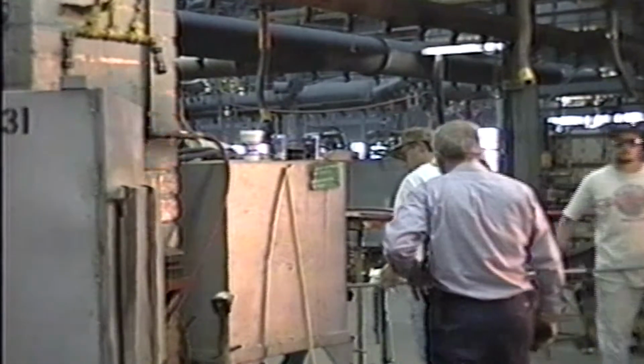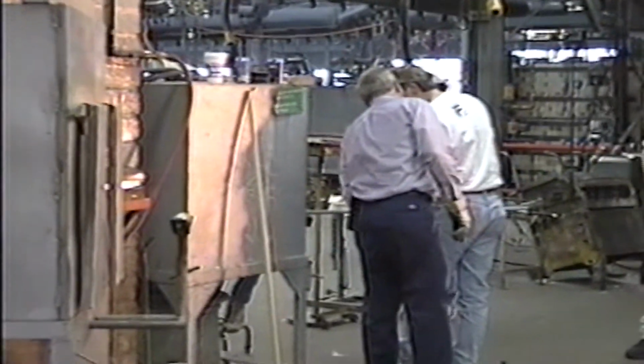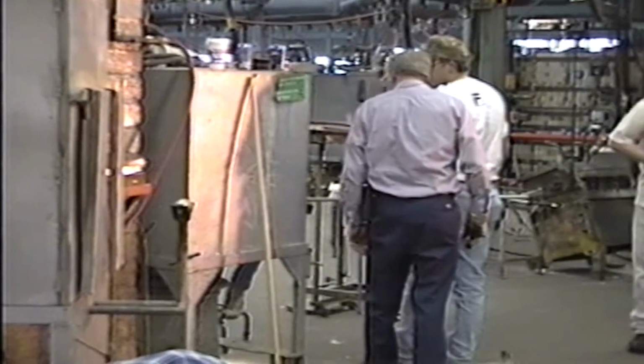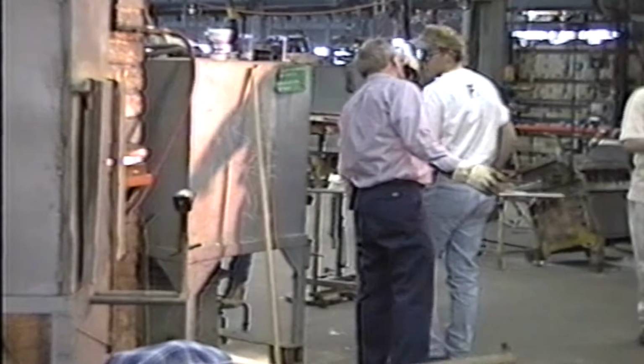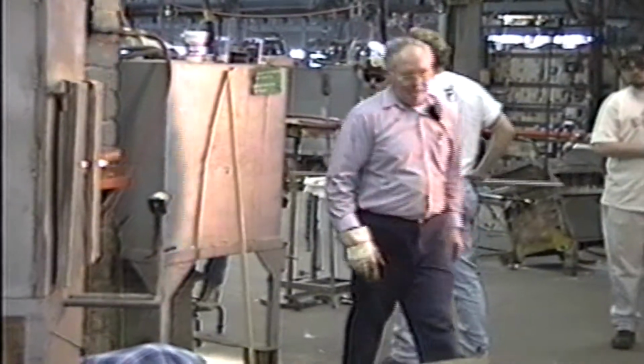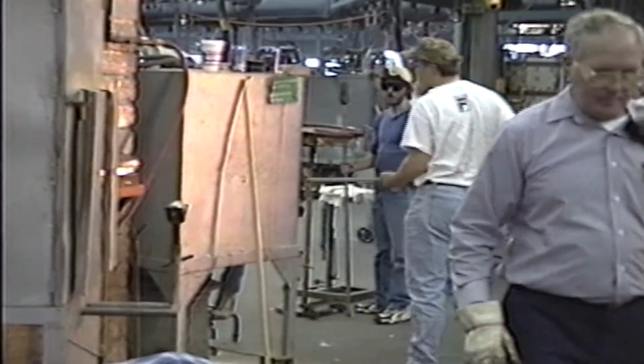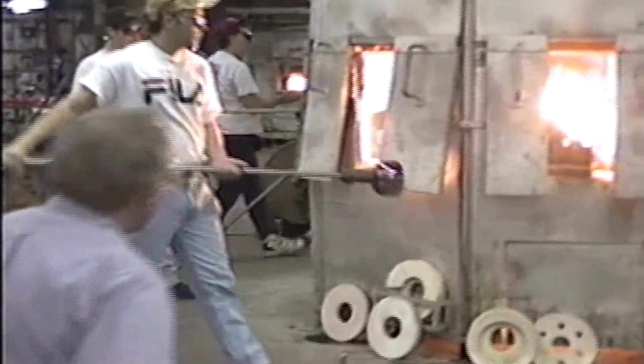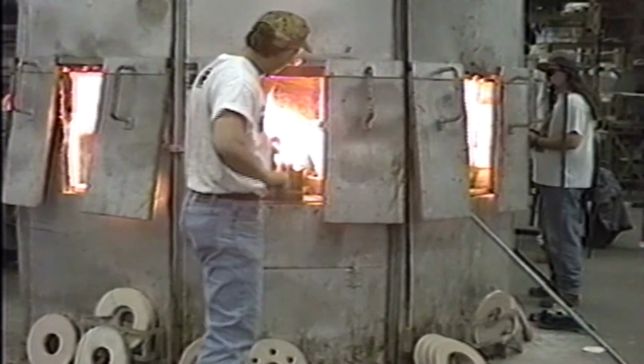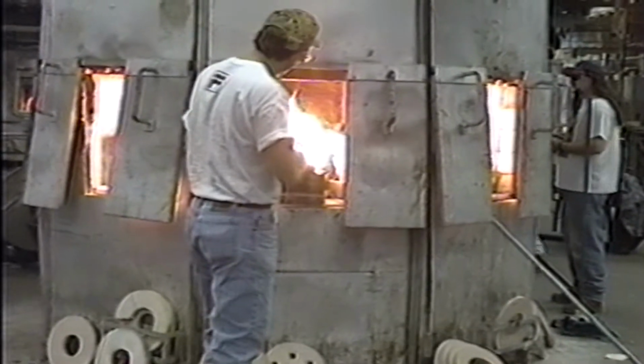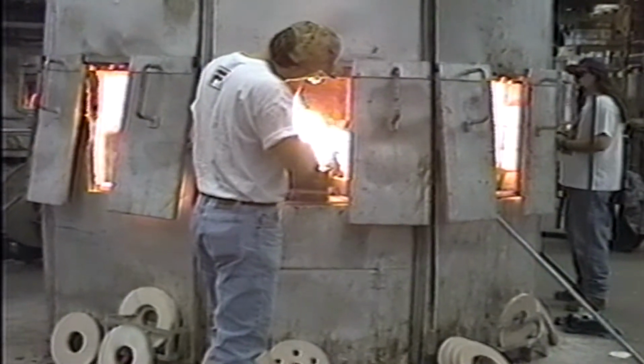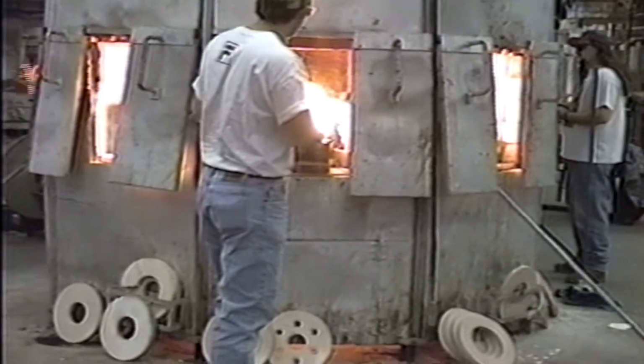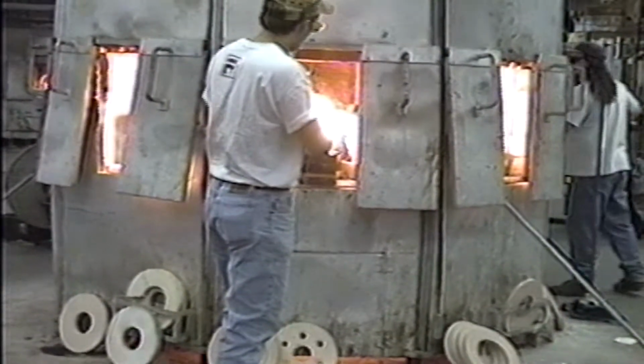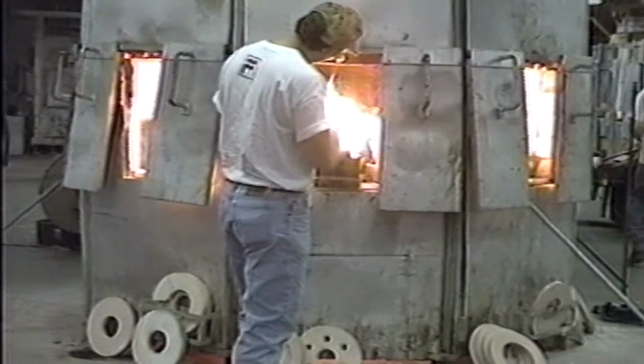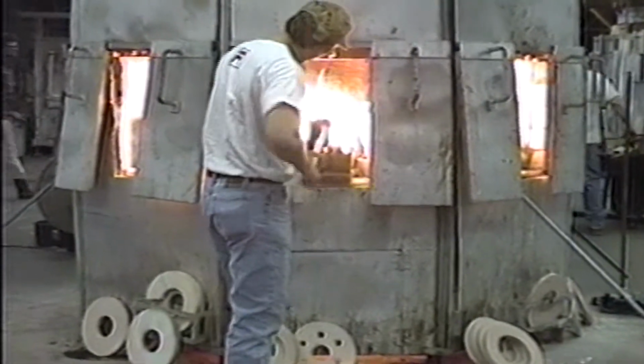Again, they're bringing over and spraying it, and that chills the piece as well. So you've got to get it re-hot or hot again, and keeping the handle hot so that the heat in the handle is balanced with the heat in the bowl is one of the problems that you have from an annealing standpoint. Because you'll notice that that handle, once it's in that snap, it never gets heated again. In hindsight, they should have probably put it on a burner or a glazer and reheated the handle before they annealed them. They probably would have had a lot more survive if they'd done that.